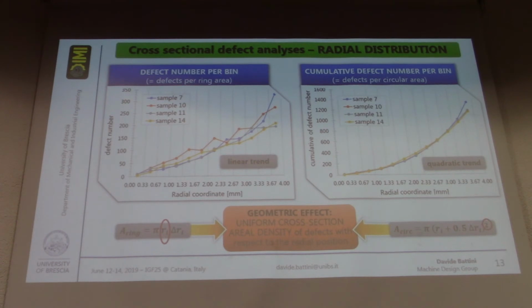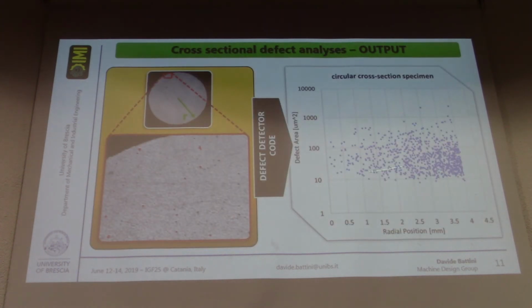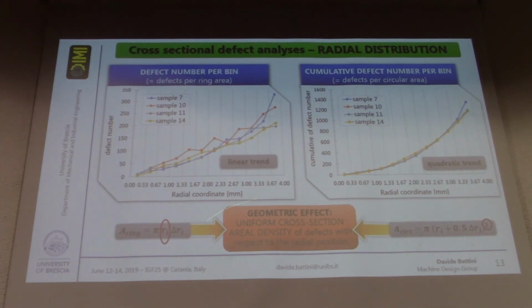So this is the first finding, which we found really interesting, in the sense that here we have the defect count per bin, which means that in each of these columns you can get how many defects there are in that specific ring. And here there is the cumulative, which is the same as not considering the ring, but considering a circular area. And as you can see here, there is a pretty clear linear trend and an even clearer quadratic trend here, which means that the defect distribution we could see here, where we counted a lot more defects in the outer region, is just due to a geometric effect.